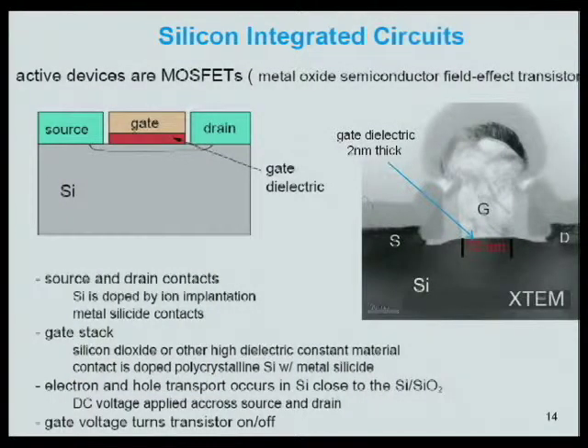And what's very important, since the current is flowing along this interface between the gate dielectric and the semiconductor, the quality of this interface is extremely important. And one of the reasons that silicon has been the dominant semiconductor material is because the gate dielectric is silicon dioxide, which is a very well stable oxide that's easy to make. And the quality of this interface is extremely good. And so that's a main reason for the success of silicon.